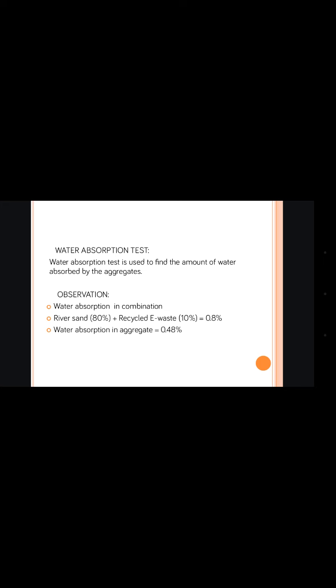Water absorption test is the most common test for coarse aggregates. The observation is that water absorption of the combination is about 0.8 percent, and water absorption of aggregate is 0.48 percent. The reason why it's more in the combined is because e-waste absorbs an extra amount of water.